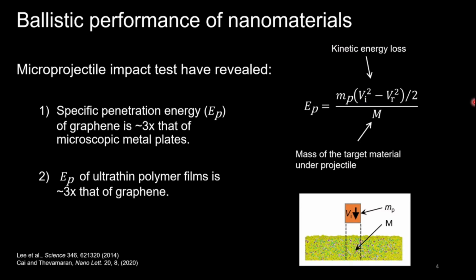Microprojectile impact tests have allowed us to study the impact response of material films thinner than 100 nanometers. Impact tests of multilayer graphene have revealed that their specific penetration energy is significantly higher than that of conventional barrier materials. The specific penetration energy EP is the kinetic energy loss by a projectile during a penetration process divided by the mass of a target material under the projectile, as shown here.